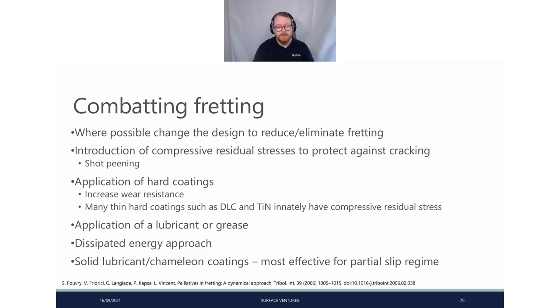Introducing compressive residual stresses, because this combats cracking, especially if you have something with a lower amplitude fretting where you have partial slip, mixed slip. So if you add compressive residual stresses, shot peening is a good way to do this. Quite extreme forms of hardening. I'll come on to that DLC question in just a second. Thank you.